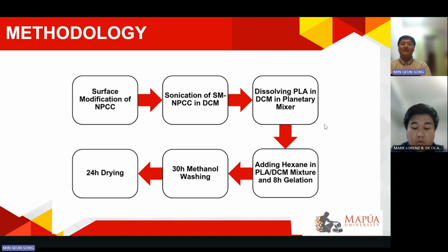0.135% of SM-NPCC was then sonicated in DCM for 30 minutes, and then mixed with PLA using a planetary mixer to dissolve the PLA, forming an 18% by weight sample of PLA to DCM. An equal amount of hexane to DCM was then added in a dropwise manner under constant stirring to initiate the NIPS process. The samples were then left to gelate for 8 hours.